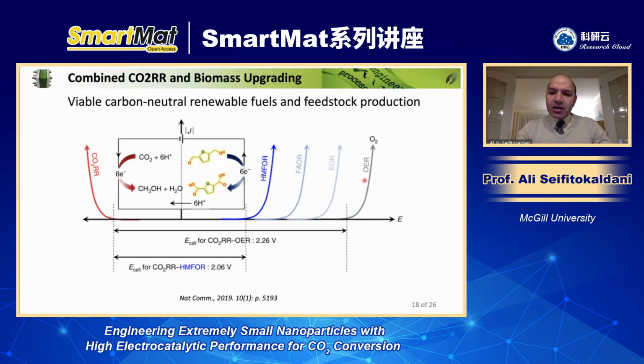So people say that oxidation of OH is too difficult, but if you have an organic compound, breaking the C-H bond is much easier than breaking the O-H bond. So organic compound oxidation must be easier and requires a smaller potential, such as ethanol oxidation reaction or formic acid oxidation reaction. Or recently, people are focused on hydroxymethyl furfural oxidation reaction, or HMF-OR. And you see here, you start with hydroxymethyl furfural, which has an aldehyde group and an alcohol group, and then you convert it to FDCA, the furandicarboxylic acid, which has two carboxylic acid groups.